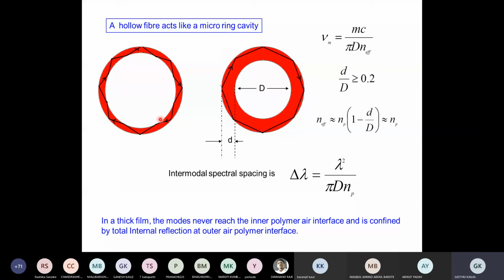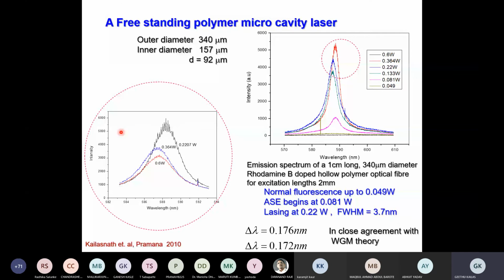And one important thing to be noticed here is that if you reduce the thickness of the tube, so this is the cross section of the fiber. Okay, this is not a ring. It has a length, and this is the cross section. And if you imagine that the polymer layer thickness is much smaller, it actually leads to a different kind of resonance. It's a normal total internal reflection. It goes to the inner interface, it goes to the outer interface. So this is a normal TIR, but here this is not going into the inner interface. It is simply circulating in the outer interface, and this is exactly the whispering gallery mode, and the observed frequencies were perfectly matched with the calculated ones.